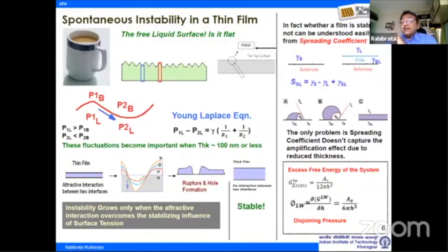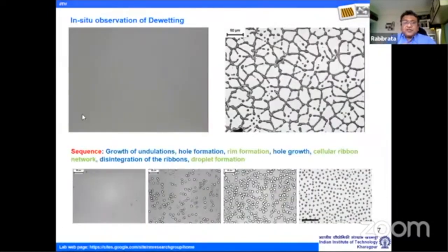And if the nature of the interaction between the film and the surface, or the top surface of the film and the substrate, is attractive, then the surface tension or the Laplace pressure, which was trying to stabilize the film, now actually has a competition. And based on the relative magnitude of the disjoining pressure and the Laplace pressure, these undulations may not stabilize any further, and the film can spontaneously lead to rupture. Right? So this is a situation.